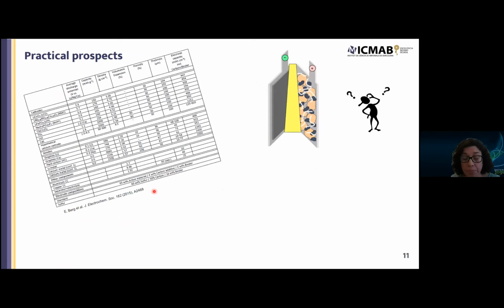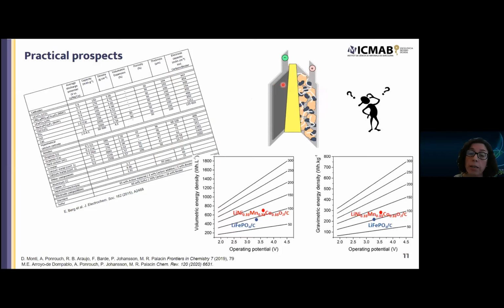So then I would like to show you some back of the envelope calculations. I told you that a priori calcium looks like an interesting anode, but could we pair this with an interesting cathode? Are the numbers feasible? So we took this Excel spreadsheet from this paper by Eric Berg and co-workers, where they estimate parameters for performance of a single cell, consisting of either two porous electrodes or one porous electrode and one metal, and they take realistic values from the lithium-ion technology with respect to porosity, density of the electrolyte, and so on. So we took this, and we just simulated cells using current collectors of aluminum on both sides, using a porous cathode and then a calcium metal anode. And this is what we got.